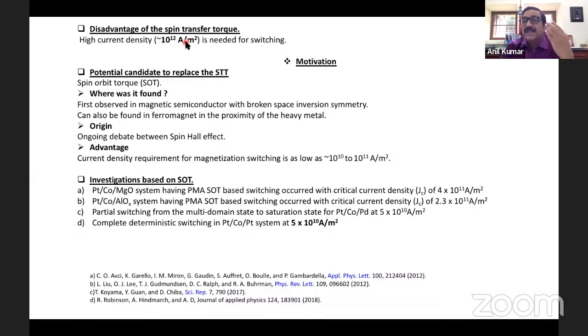If I am reducing the electrical current by a factor of 10, I'm saving the electrical power by a factor of 100. Because when you pass electrical current through these structures, there is something called Joule heating. The Joule heating is I squared R, where I is the current. If you can reduce the current by a factor of 10, since I squared is there, I can reduce the power consumption, or the power dissipation or loss, by a factor of 100. So that is very relevant.